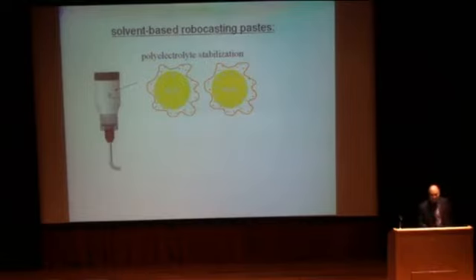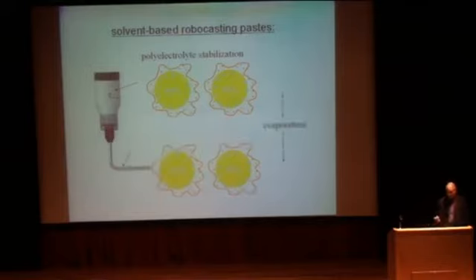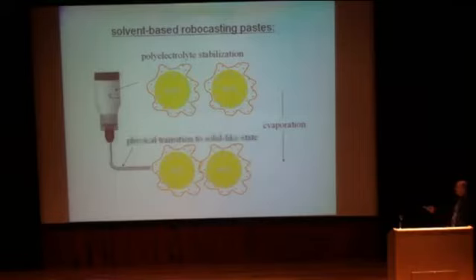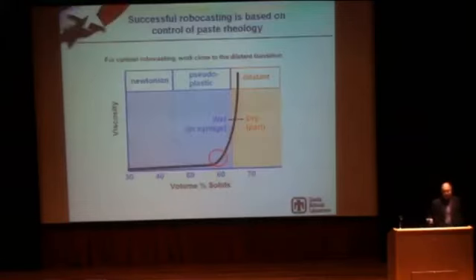We're using polyelectrolyte stabilization to work closely to that pseudoplastic regime, and then with just a little bit of evaporation, we can have a pseudoplastic, pliable slurry inside the syringe. After deposition, with just a little bit of evaporation, we increase the solids loading just enough to make this material now behave like a solid, even though it's still totally wet. From a standpoint of viscosity, in the syringe we're working with pastes that are very close to this solids loading where the viscosity is... So in this case, it's pseudoplastic and very pliable.